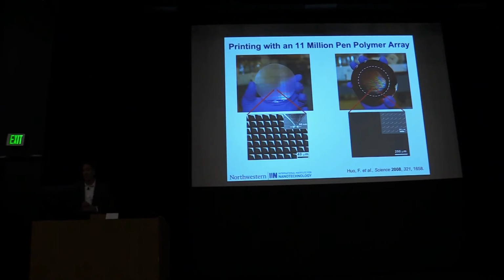And here you can see an array of 11 million of these pyramids, all almost identical to one another. Comes down to 60 nanometer radius of curvature. That's what allows you to really exceed, for example, the resolution of conventional contact printing types of experiments. Put this in an AFM after it's been coated with molecules, in this case mercaptohexadecanoic acid, bring it down 4 times, and now in a matter of seconds you're making millions, 44 million features across many square centimeters with sub-100 nanometer resolution. That was pretty neat.